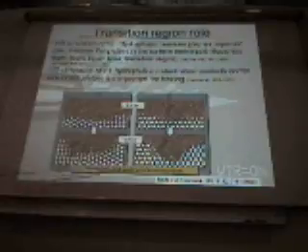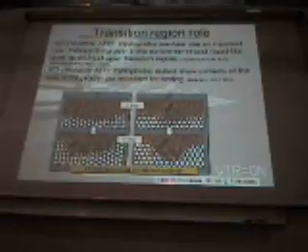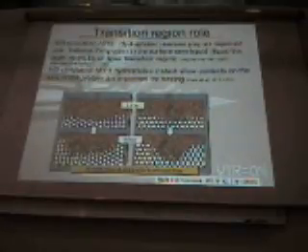And also, this is one example which was obtained by MD simulation. And my colleague Nada did this kind of simulation. And you can see here, this part is the protein, and here's the ice, and here's the water. And the interface between ice and water is a very diffuse structure. And so the diffuse structure interacts with the protein. I think this is one of the views of interactions between ice and proteins.